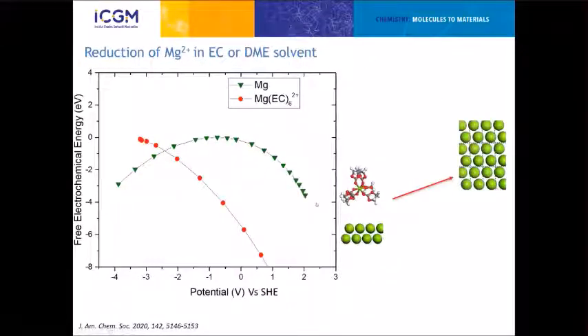Now, the first step of our study was investigating the simplest reaction, that was the transformation of magnesium 2+ into magnesium metal at the interface. We did a study on the different solvation spheres, and we find always some kind of octahedra around the magnesium. We did it for two solvents. The classical one used in the classical carbonates used for lithium, which is of course not the best for magnesium, and we are able to get the reduction potential in ethylene carbonate. That will be minus 2.37 versus standard hydrogen electrode. That is very close to the experimental data that is around minus 2.4.